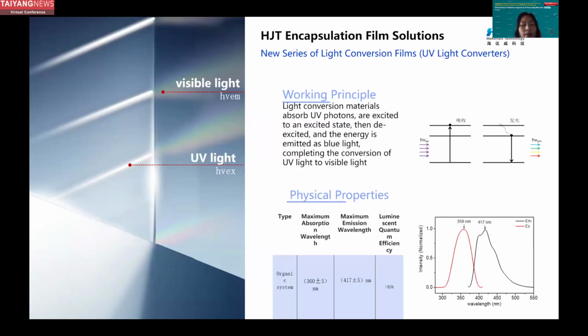Okay, that is the first part, on TOPCon. The second part is about the heterojunction. We all know that heterojunction is very sensitive to UV light. We, as an encapsulation films manufacturer, will solve it with some anti-UV agent. In the early days, we used double-sided UV cutoff film or single-sided UV cutoff film as encapsulation solutions. Later, we began to change the application to conversion film.